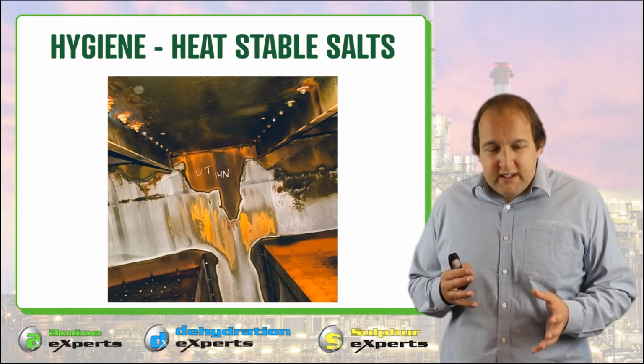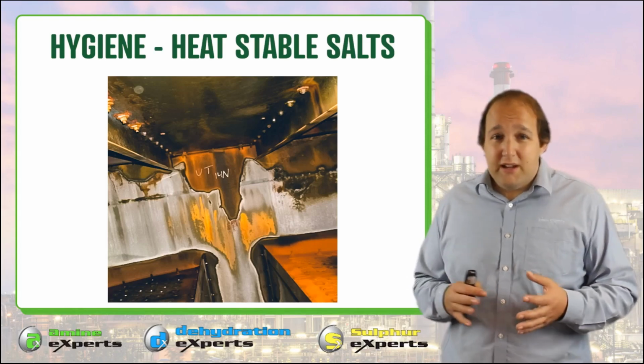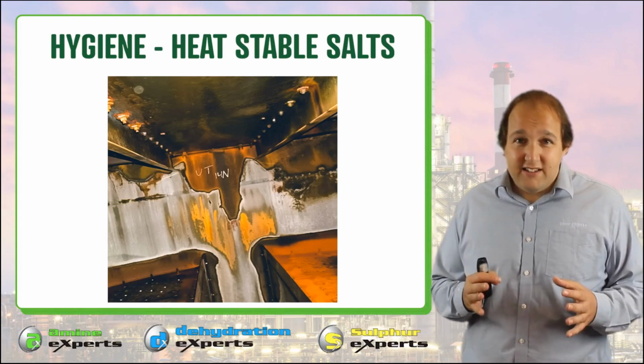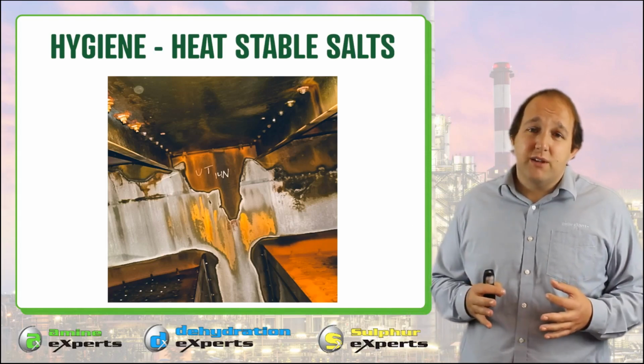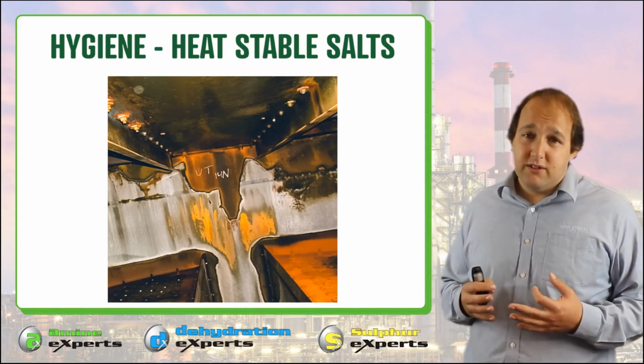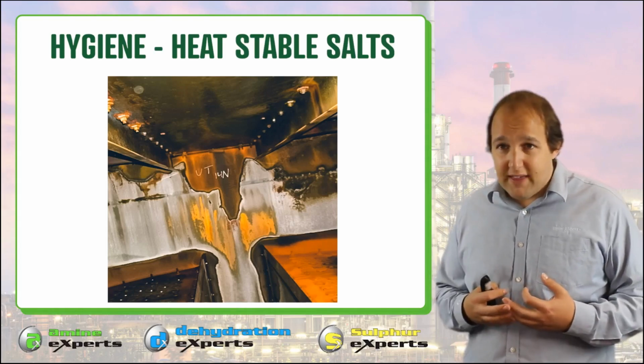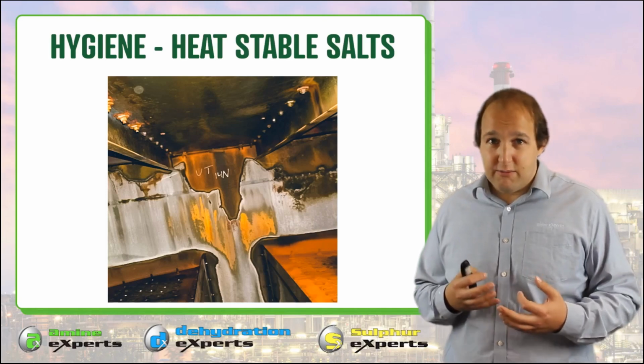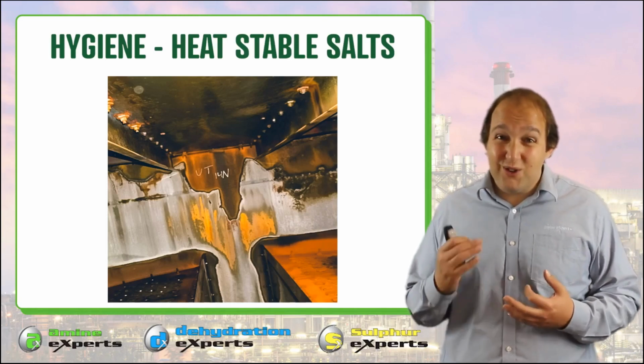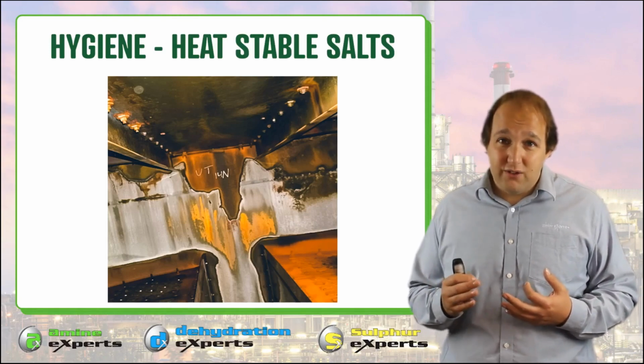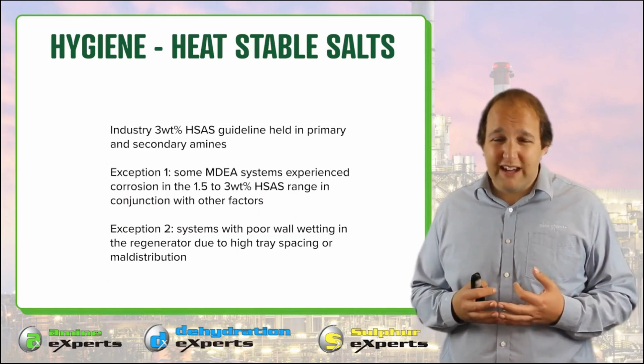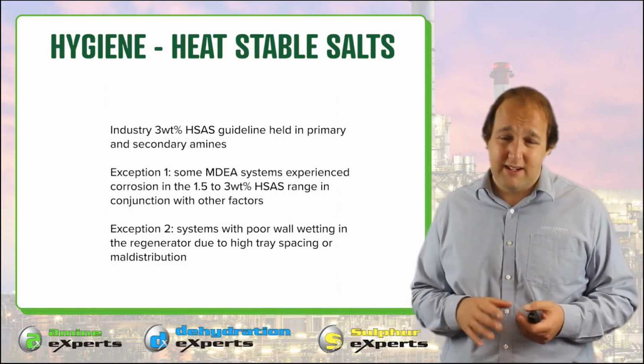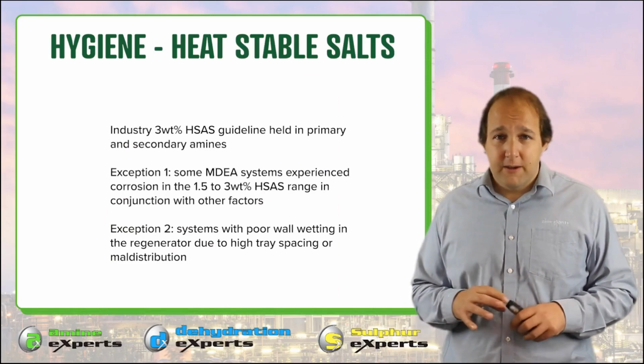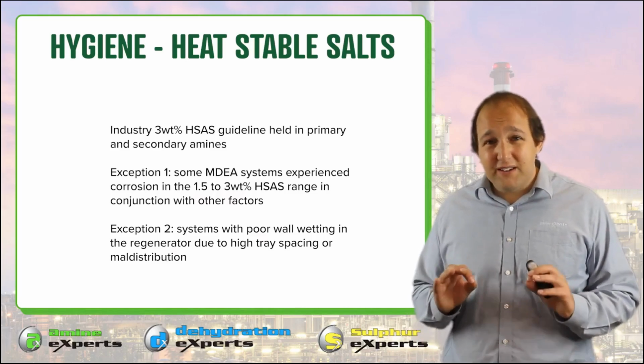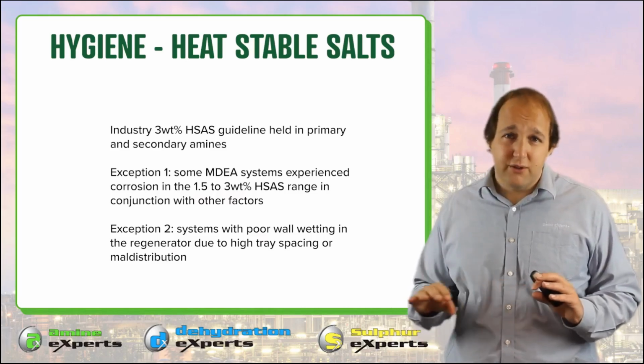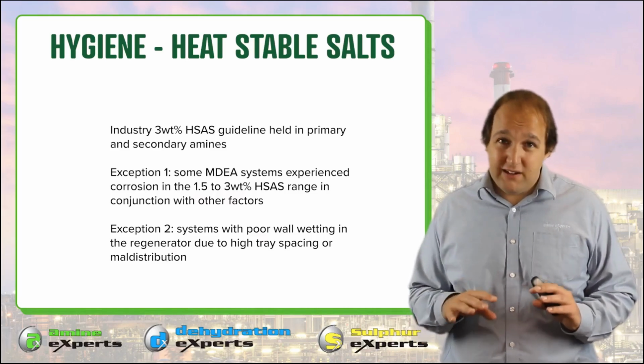Historically, back in the dark ages of the 1980s, they'd say 10% of amine strength was the maximum level of heat-stable salts. When MDEA and other higher strength amines came to market, that no longer held. We found carbon steel could not really handle higher concentrations like 4 or 5% of heat-stable salts. So now the industry has moved to a 3% limit as your maximum heat-stable salts. When we looked in detail at the failures that we'd seen, we saw that generally this 3% limit held true. We did not see many failures below 3%.